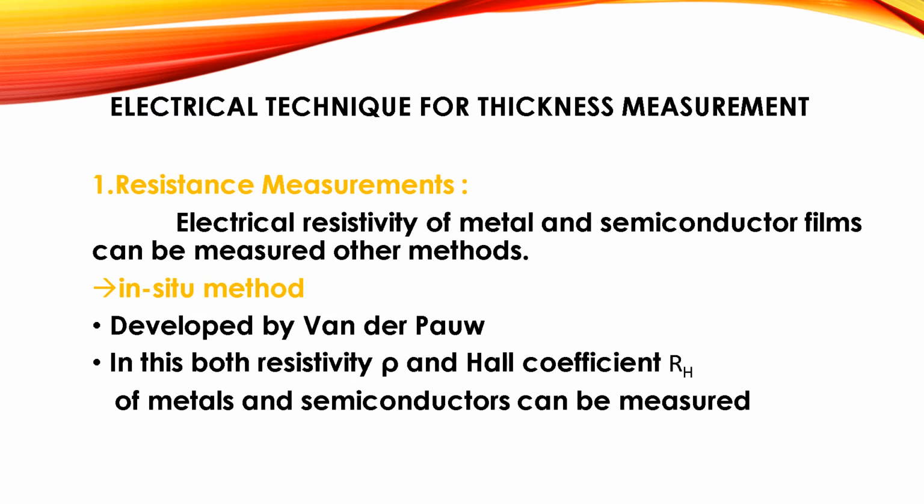The electrical resistivity of metal and semiconductor films can be measured by other methods. One of these is the in situ method developed by Van der Pauw in 1958. In this, both the resistivity and the Hall coefficient of metals and semiconductors can be measured.